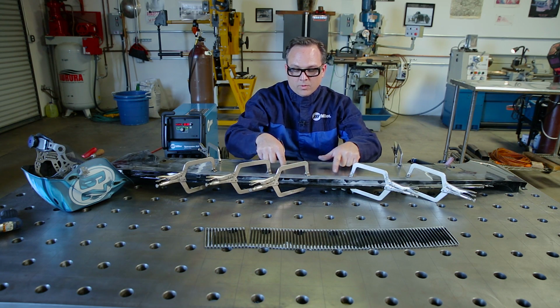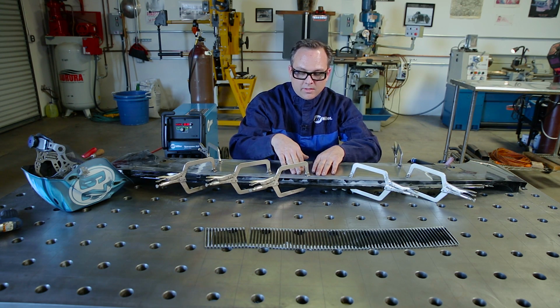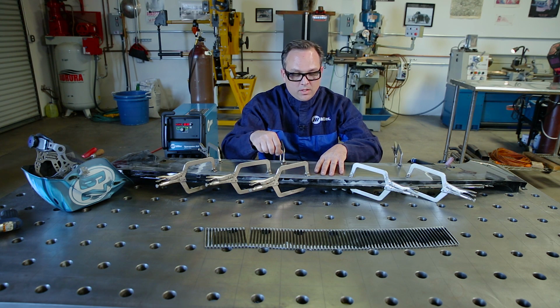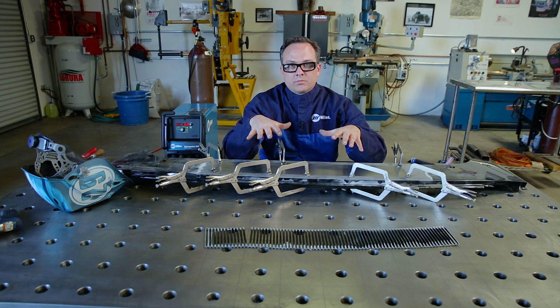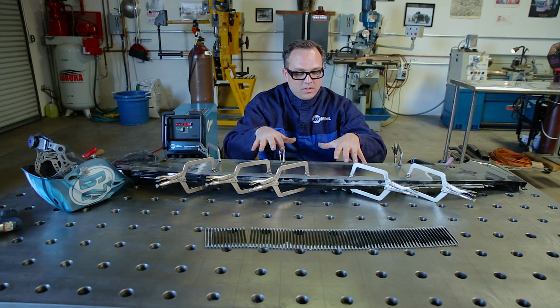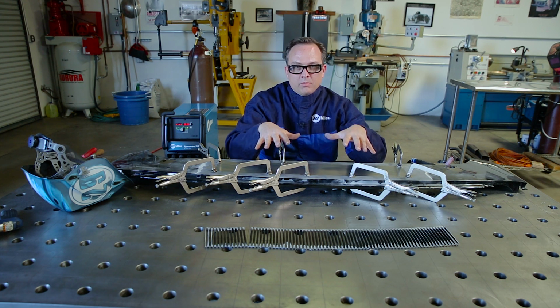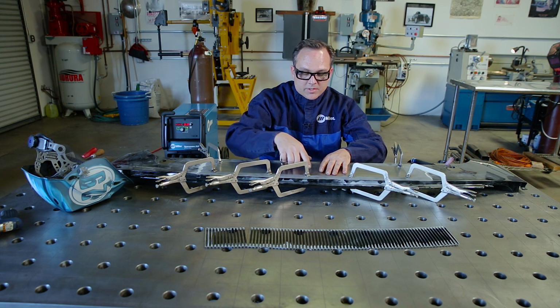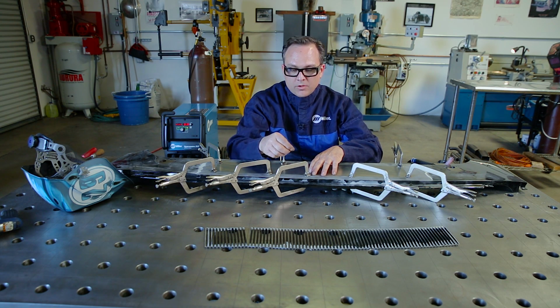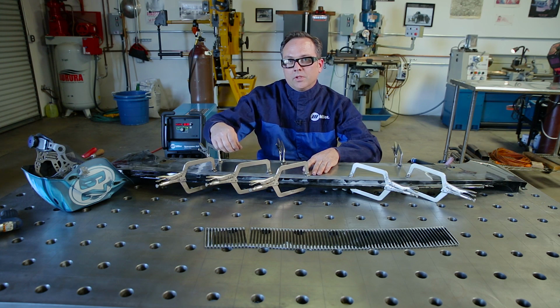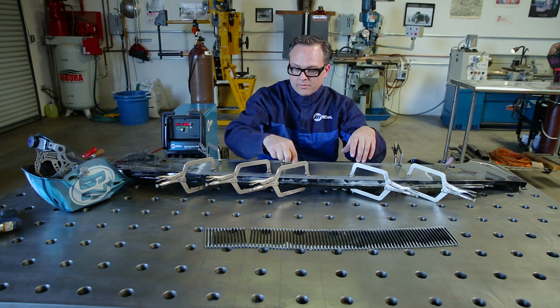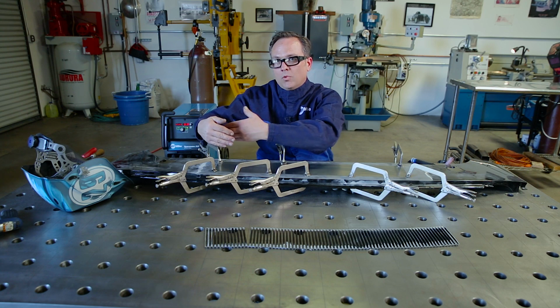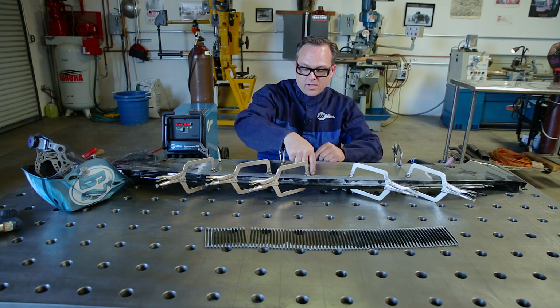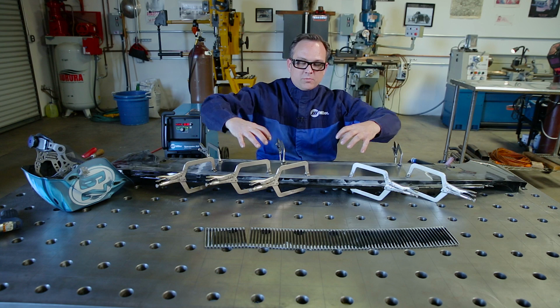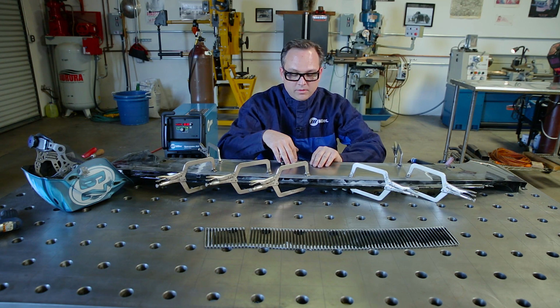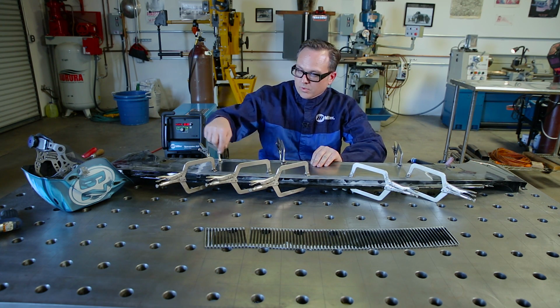So if I start in the middle and work my way out, I can actually use that to help tighten my joints. And since we scribed it when everything was completely stress-free and relaxed, that scribe mark is really where the metal should be when we wind up. So by starting in the middle, each tack you put in it actually will tighten your joint. It shrinks the metal, so every tack I put in it, it tries to close that gap more and more as you work your way around. So if I start here and then I jump here and around, it starts moving things all over the place, and we don't want that. So I will start in the middle and work my way around.